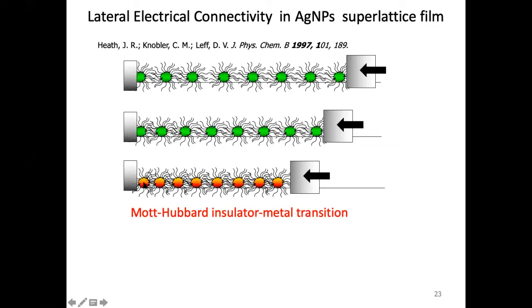Now the electronic wave function of one particle will overlap with the electronic wave function of the other particle. I think you remember this tunneling effect in the particle in a box problem, a finite size well, where there is a finite probability of finding the wave function outside the box. Exactly the same thing happens over here. Here my box is spherical; that's the only difference. So now my particles are so close that there's a finite overlap between the electronic wave function of this particle and that particle, and this film suddenly becomes conducting. It was insulating, now it becomes conducting. This transition is called the Mott-Hubbard insulator to metal transition.